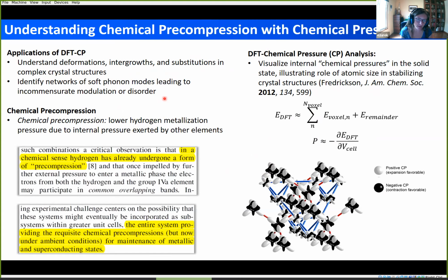We thought this would be a really interesting technique to apply because it also lets us visualize the chemical pressures within the system, which goes along with Ashcroft's hypothesis that you could use this type of chemical precompression to add chemical pressure within the hydrogenic lattices. So just to let you know, this DFT chemical pressure technique basically expands and contracts the cell and does a DFT calculation.